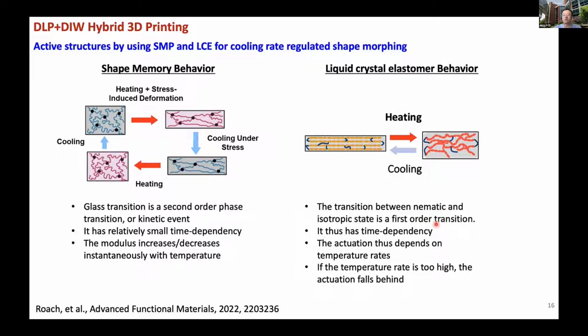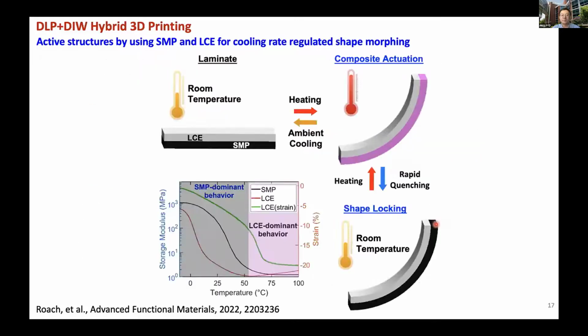So there's a time difference between the transition of shape memory behavior and the liquid crystal elastomer behavior. Here we're trying to utilize this time difference to create interesting structures. Here's the idea: if I can print LCE on shape memory polymers, then when I heat it up, the SMP becomes soft, and my LCE starts to contract. So this will give me this kind of bending deformation.